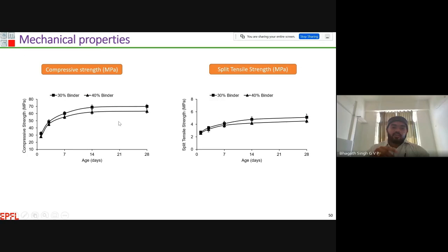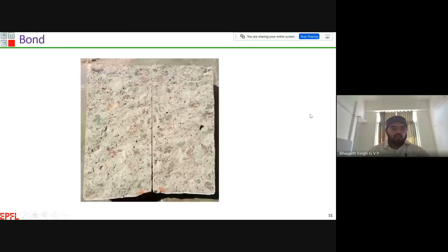And these are the mechanical properties we have determined for 30% binder and 40% binder. With 30% binder and 70% aggregates, I can achieve about 72 megapascals. With 40% binder, I can achieve about 62 megapascals strength. In the case of split tensile strength, we have observed similar trends.